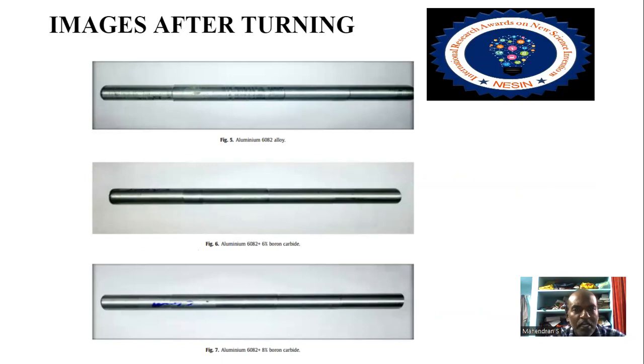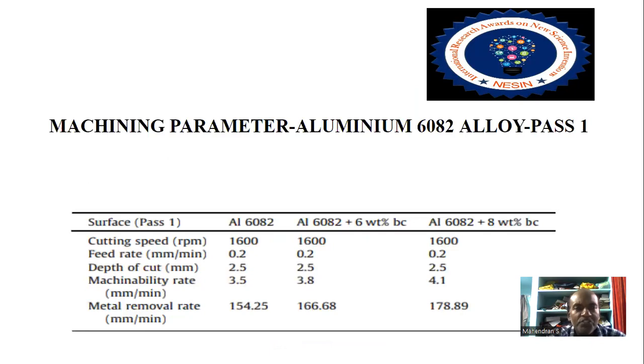Aluminum 6082 alloy, aluminum 6082 plus 6% boron carbide, aluminum 6082 plus 8% boron carbide. These are the various machining parameters. For aluminum 6082 alloy, these are the constant values: cutting speed 1600 RPM, feed rate 0.2 millimeter per minute, depth of cut 2.5 millimeter. Machinability rate is 3.5 to 4.1, and metal removal rate is 154.25 to 178.89. So the machinability rate and metal removal rate gradually increase at constant cutting speed, feed rate, and depth of cut.